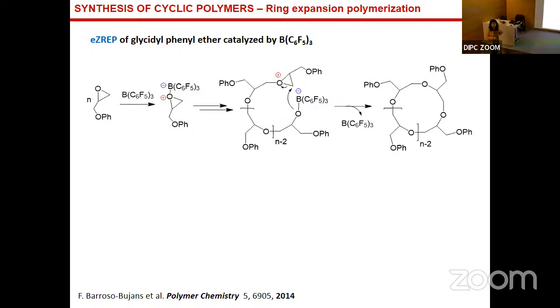another kind of monomer, which is an epoxide. But this mechanism seems to be also zwitterionic, but not nucleophilic, but electrophilic, because this catalyst attacks the monomer electrophilically. It looks for electrons here, and then starts to open the monomer and to generate this growing chain also by a zwitterionic mechanism. And at the end, the catalyst is released and forms this cyclic polyether. And we found that by changing these groups here, with these side groups, we can obtain cyclic polymers with different functionalities.